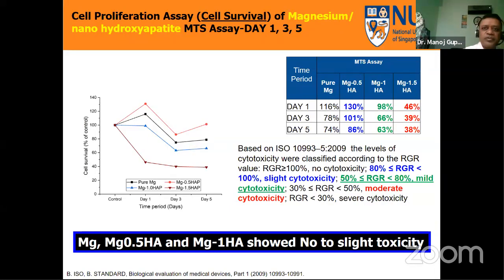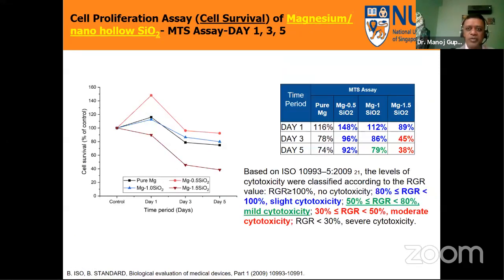We also looked at cell survival studies. The blue numbers in this table show no cytotoxicity, green shows mild cytotoxicity, and red shows moderate cytotoxicity. Obviously you want no cytotoxicity or mild cytotoxicity, so magnesium 0.5% HA and magnesium 1% hydroxyapatite are the ones to further focus on.